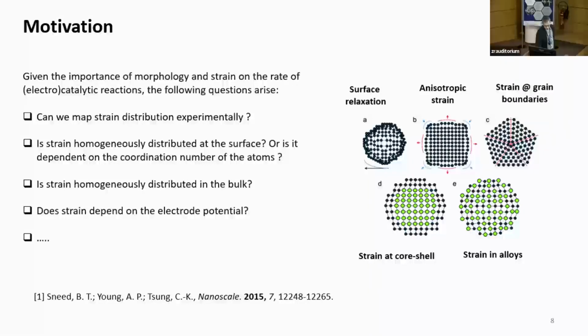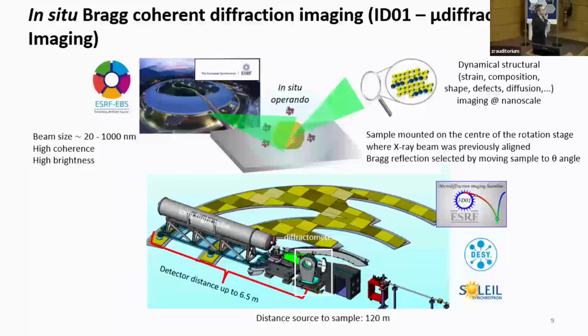Well, essentially, to get insight into this, we use Bragg coherent diffraction imaging. So this is not a new technique. It was developed at the beginning of the 2000s, but thanks to the ESRF EBS source, now it becomes possible to work on a single platinum nanoparticle and to study the very same particle in situ operando, so under catalytic reaction conditions.